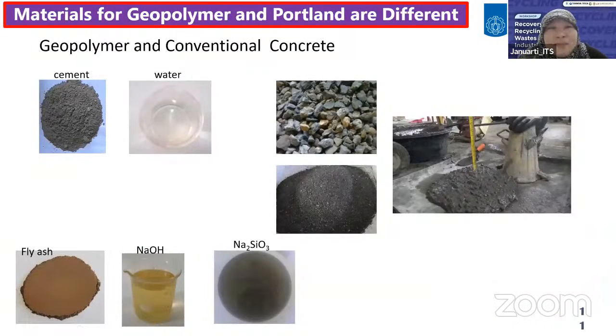And talking about the difference between the geopolymer and conventional concrete here, we use fly ash 100% to replace cement, and we use alkali, usually natrium or sodium, to replace water. And as usual, we can combine bottom ash and sand together with gravels to make concrete. The appearance is the same. The workability is also the same. The mechanical properties are also the same.